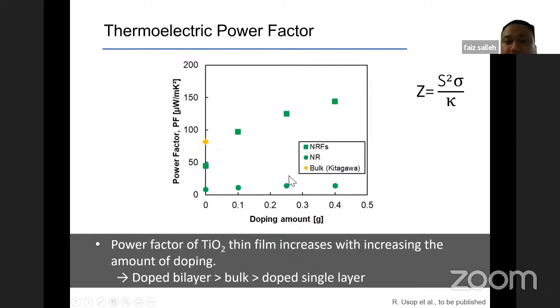So we just measured at one temperature, and we can see here that the nanorod, nanoflower, which is the bilayer, can be improved by using doping. We can see here it is improved around 3 times larger compared with the undoped. I did not put the magnified graph. Actually, if we magnify this part, the nanorod also increases a little bit compared with the undoped. So here we can see that by doping, we can improve the thermoelectric power factor of the bilayer, which is larger than the bulk TiO2 and also larger than the nanorod.